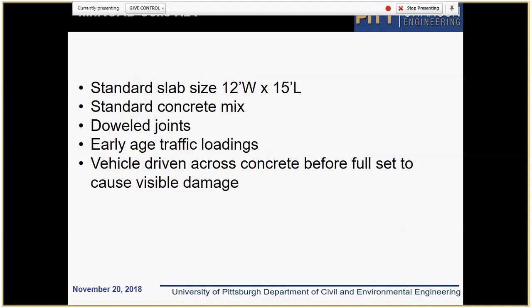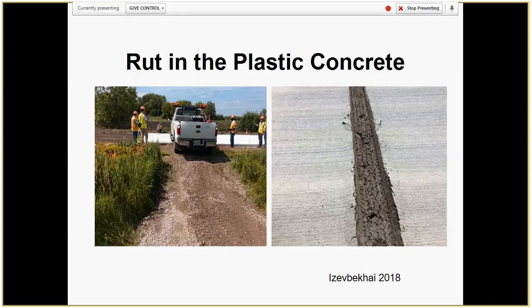It uses a standard concrete mix, and for one cell, the vehicle was driven across the pavement while the concrete was still plastic, and that caused visible damage. But four sections were loaded at early age, after the concrete was set, and one section was left as a control section. So this slide shows an example of ruts created in plastic concrete. It illustrates that opening to traffic too early is not a good idea,